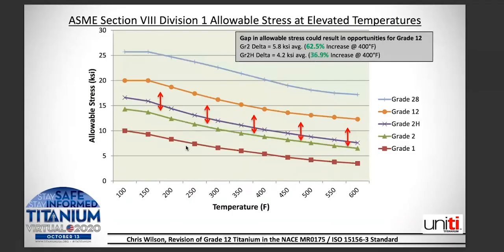Now, when we look at those, just on an allowable stress at elevated temperature and chart those out by temperature, you can see that grade 12 has a significant improvement over the routinely available grade 2 grades. The gap in the stress for grade 12, if we're looking at a grade 2 delta, there's a 5.8 KSI average. That's a 62.5% increase at 400 degrees Fahrenheit.